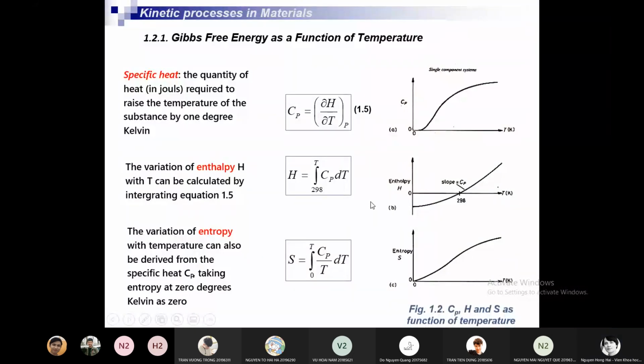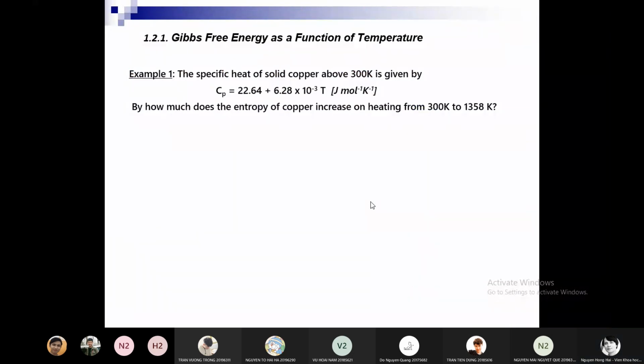So we have an example. The specific heat of solid copper above 300 degrees Kelvin is given by this equation. The specific heat of solid copper Cp is equal to 22.64 plus 6.28 multiplied by 10 to the power minus 3 T, in joule per mole per degree. So the question: by how much does the entropy of copper increase on heating from 300 degrees Kelvin to 1358 degrees Kelvin, which is the melting temperature of copper?